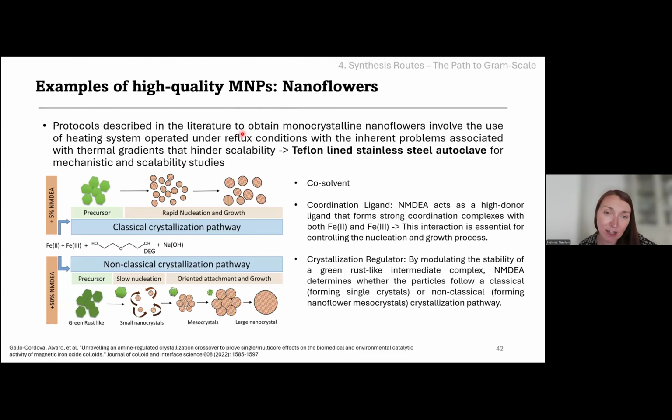And here the use of the amine, the NMDEA, is very important because it's not only a co-solvent, but it also has important coordination properties. It acts as a high donor ligand that forms strong coordination complexes with iron 2 and iron 3. And this interaction is essential for controlling the nucleation and growth processes.